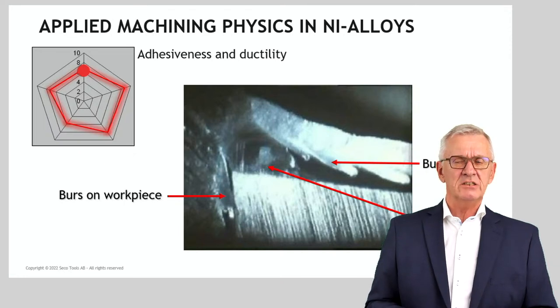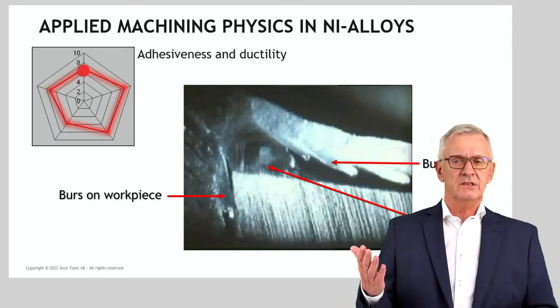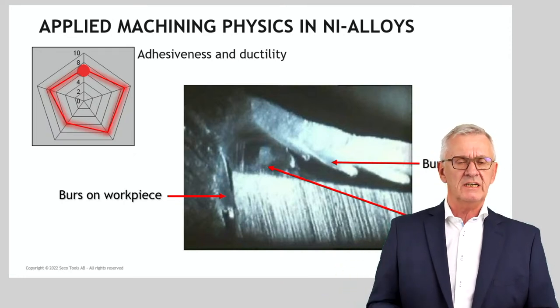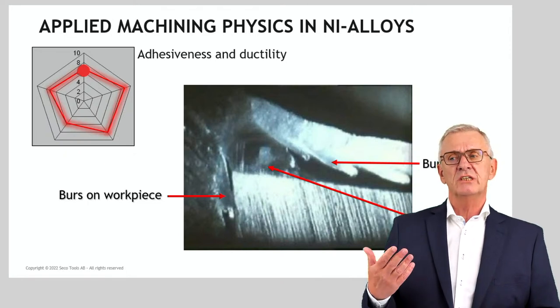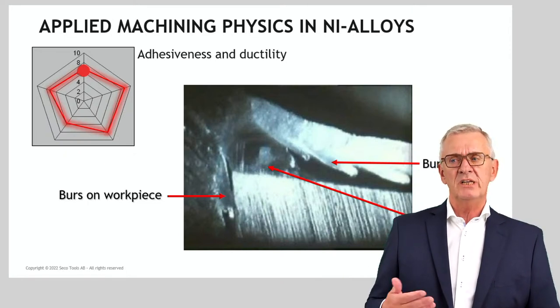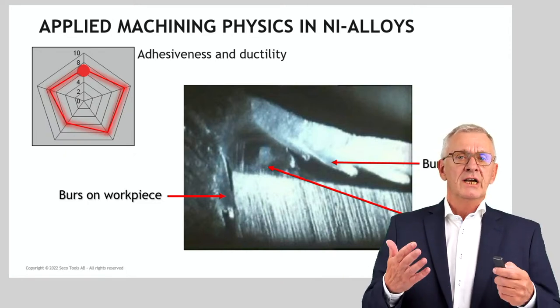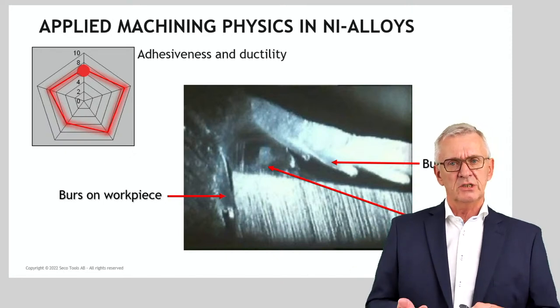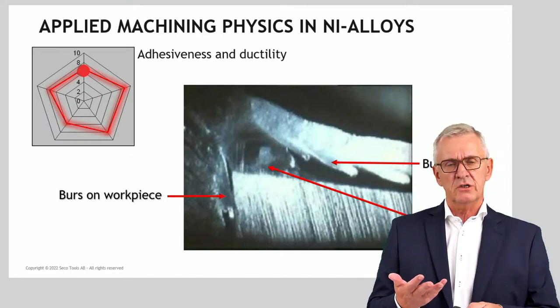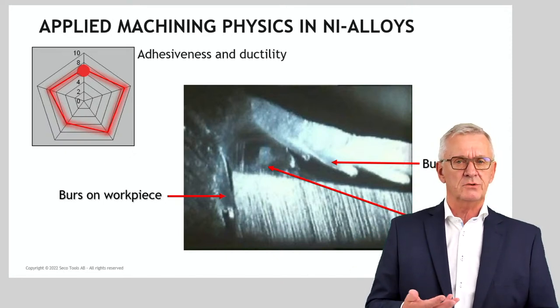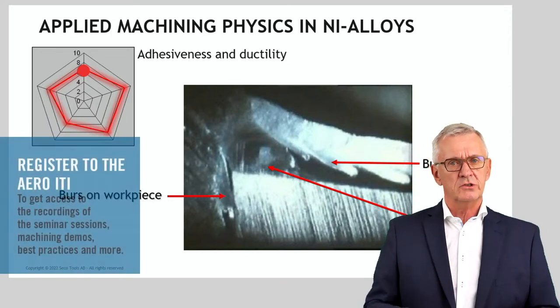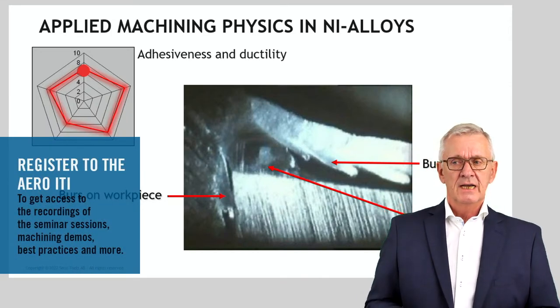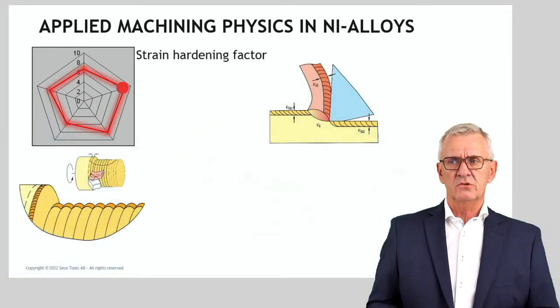So adhesiveness in case of superalloys is something you have to watch out for, because it would lead to build-up edges, and build-up edges are going to destroy everything in the process. The chip formation will be different. The surface roughnesses of the machined surface will be different. If you see microburrs on a surface, it's adhesiveness effects you see. Adhesiveness is something to watch out for.